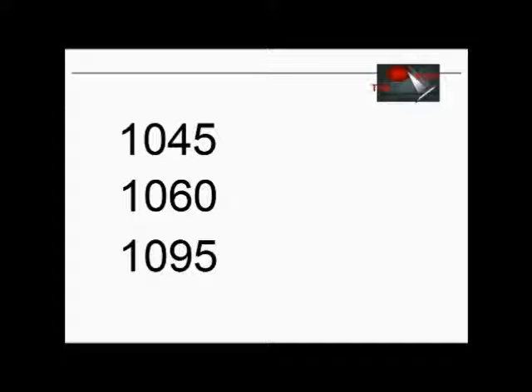This brings me to the first issue. Now this is important. A steel with more than 0.22% carbon content has very bad welding properties. You should not even think of trying to weld a European sword blade because it has for sure at least 0.45% carbon and can have easily 1% carbon if it is made out of 1095 steel. So a welded rod on a blade is absolutely a no-go.